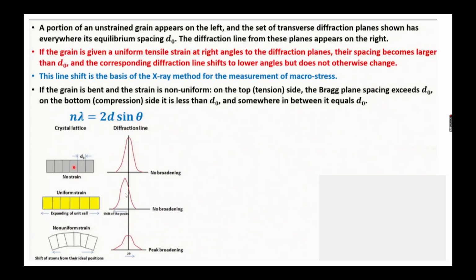Okay, but in the question it is asking about the uniform strain. So when the uniform strain is there, your peak will shift towards the left. As you can see here, it is at the exact center, but with respect to the first one, the maximum of the peak is at the left as compared to the no strain sample. If the grain is bent and the strain is non-uniform, the Bragg plane spacing exceeds d naught on one side, and on the bottom side it is less than d naught, and somewhere in between it is d naught. So here you will get a peak broadening.